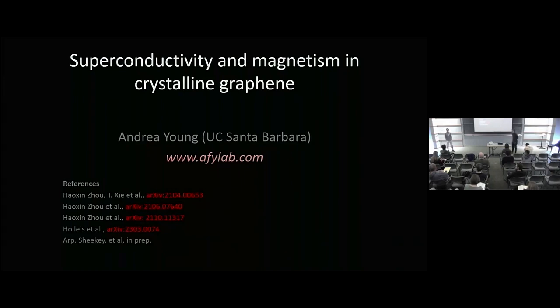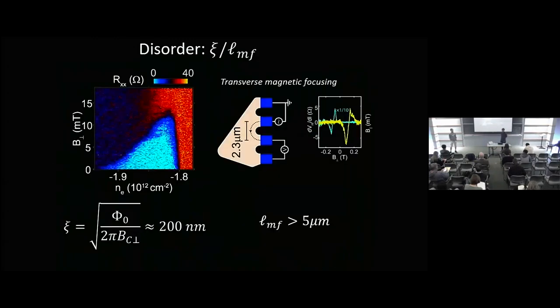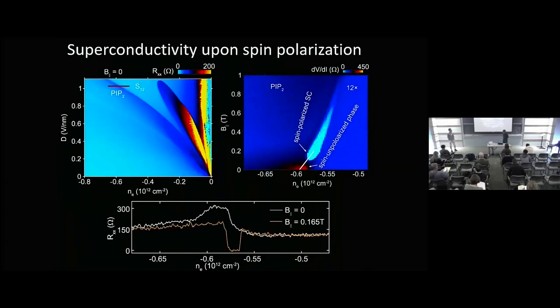Thanks. This was a stimulating talk. I have a question about the competition between singlet and triplet that you referred to earlier, with reference to the absence of superconductivity in zero field, but you see it in finite field. Have you considered the possibility that there could be a competition between three triplet order parameters and the fact that the magnetic field breaks that degeneracy? One of the ways in which that might be supported would be if you add some spin-orbit coupling so that the d vectors could feel the anisotropy of the lattice, but you seem to have already done that. So that seems to suggest that. Another possibility would be to do the field in a different direction. So the question to you is, do you see this field-induced superconductivity when you turn on out-of-plane fields? No, of course not, because there's such a strong orbital effect at that point. So you certainly can't, and you don't. But that's not too surprising.